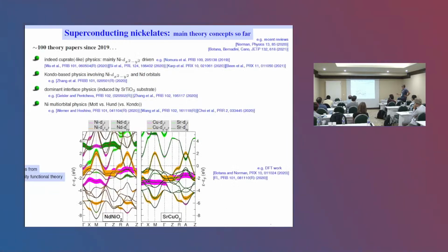There are these two differences: we have the self-doping band in the nickelates, which we do not have in the cuprate. And another important thing that I also want to put forward here is that the nickel d_z² is quite far away from the Fermi level, in the occupied part, in the cuprate compound, whereas it's quite close already in the nickelate. I mean, it's like minus 1 eV, it's not super close, but it's still close on the DFT level. Furthermore, as seen by these fat bands, this actively hybridizes into the self-doping band. So the nickel d_z² is already right from the beginning a vital player.